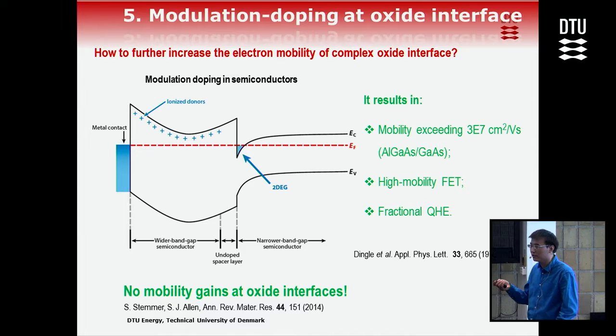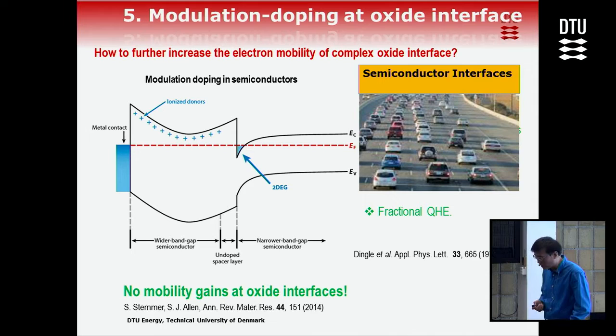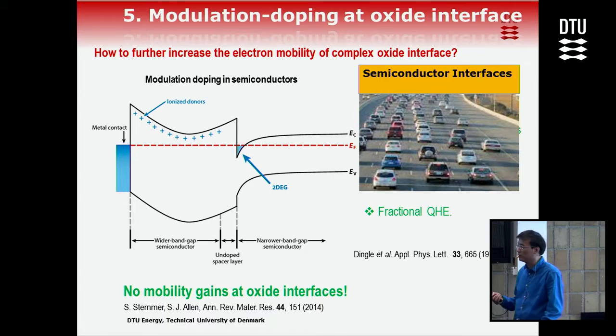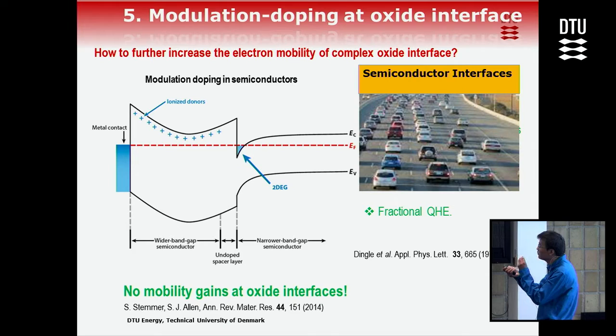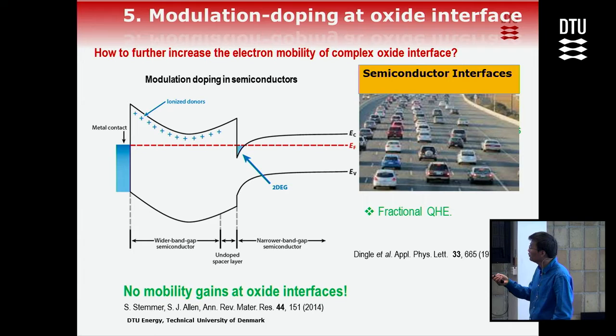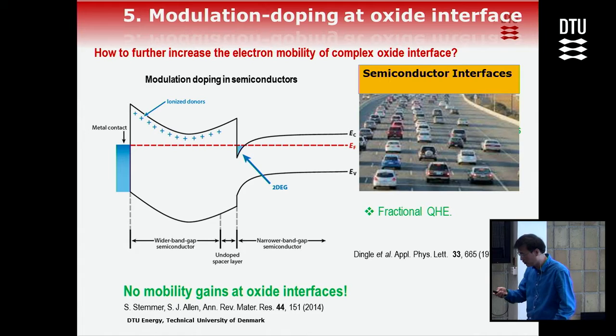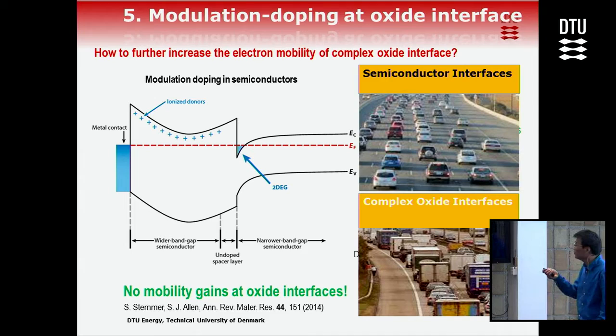This technique is very useful, but until 2014 nobody had succeeded in applying it to oxide interfaces — nobody got any increase in mobility. We think this is because in semiconductors modulation doping separates electrons from the ionic donors to suppress scattering. If the electrons are cars, the donors are like fences on the highway. But in oxides, electrons are coupled — you have not only cars but also trucks — and when cars move together with trucks they won't move fast.